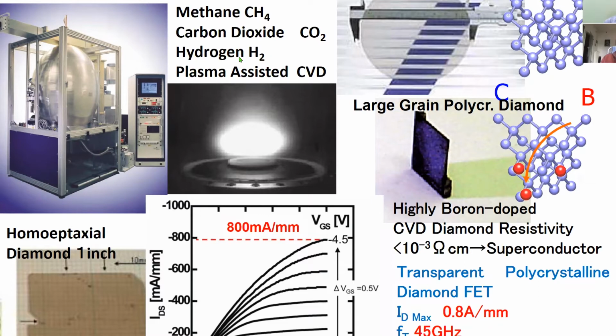So we are using methane and oxygen, CO2 and hydrogens to form the diamond. We use the plasma-assisted chemical vapor deposition technique, where the methane and hydrogen are decomposed into the atmosphere. But this atmosphere is relatively low pressure, because it's less than atmospheric pressure.